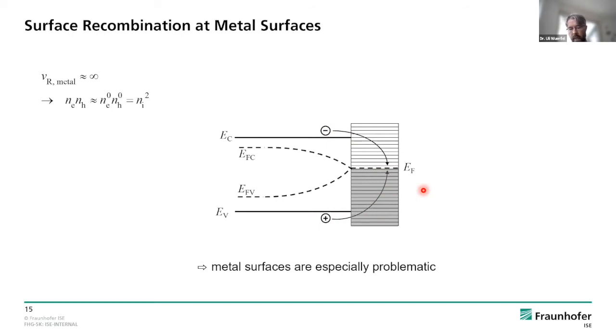So in other words, we can say that at a metal surface, if an electron and a hole arrive there, they are lost. No chance. This is now, of course, an extreme case where you can also see the quasi-Fermi levels. Remember, these are the electrochemical potentials, so a gradient in this is the driving force. Here you can see that you have a bending, so you have a gradient in the quasi-Fermi levels. This drives electrons and holes to the same surface. So you don't necessarily have an electrical current, but you have at the same time an electron current and a hole current, summing up to overall zero. But it means that you lose charge carriers there.